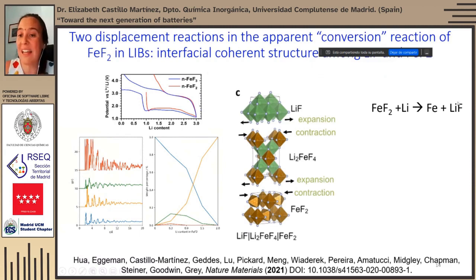So instead of explaining this reactivity with a one-step conversion reaction, we could explain this reaction as a two-step displacement reaction where lithium ions displace iron from the sublattice, and then the insertion of further lithium ions can completely extrude the total amount of iron.